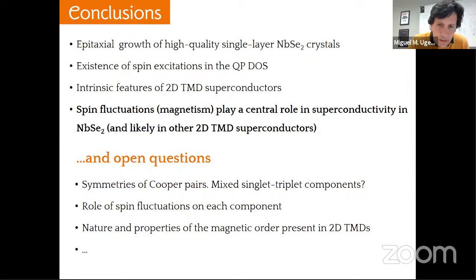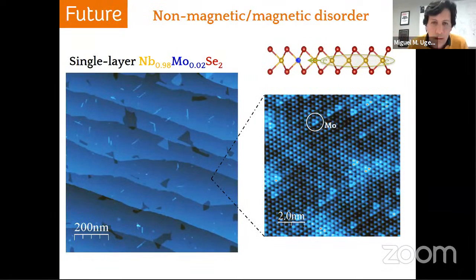So if I have a minute, I would like to give you some flavor about the further work that we are doing now. If you remember, I told you that conventional superconductivity should be highly sensitive to magnetic disorder. So what we are doing now is to study the superconducting state using alloys instead of pure niobium diselenide. We embed single atomic impurities, like in this case, for example, isolated atoms of molybdenum replacing niobium atoms, and we are studying the superconducting properties around these atoms.